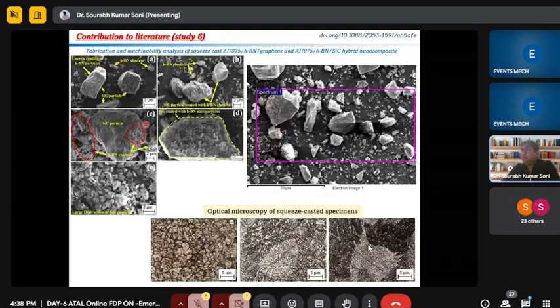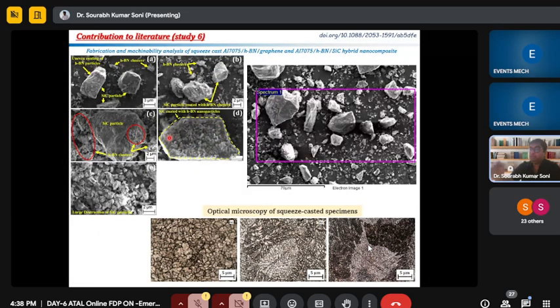And this one is the same image of SiC HBN nanoparticles. Here we can see the coating of HBN nanoparticles over the SiC particle with the increment in ball milling duration. Here we can see the agglomeration destruction and particle destruction also. This is the same EDS. EDS I have not attached because we have observed the SiC and HBN over the SiC particles. So from here we can say very uniform dispersion and no agglomeration kind of behavior.